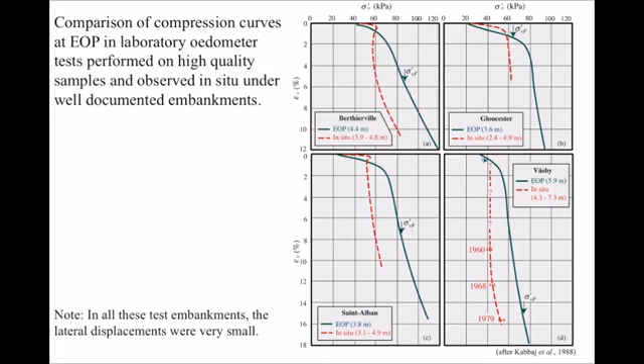And this has been done and compared under 4 test embankments: Berthierville, Gloucester, Saint-Alban, and Väsby in Sweden. And we have in green the compression curve obtained at the end of primary consolidation on high-quality samples, and in red, that's the in situ curve. And we can see that in all cases, the in situ compression curve is below the compression curve obtained at the end of primary on high-quality samples in the lab, which is indicating that at least hypothesis A is wrong.